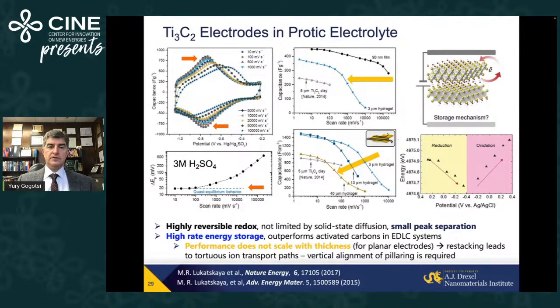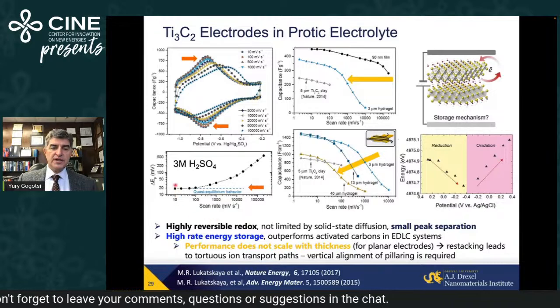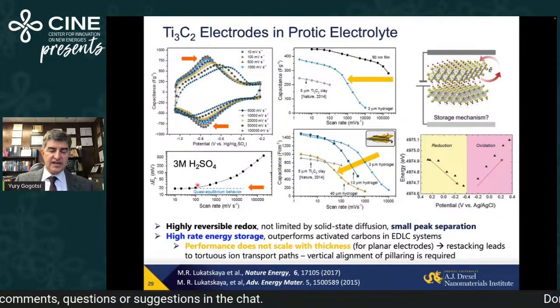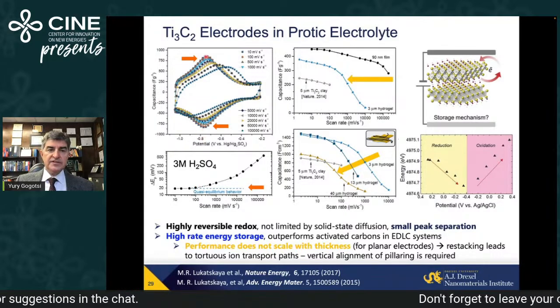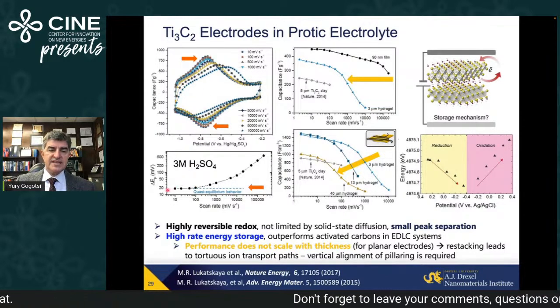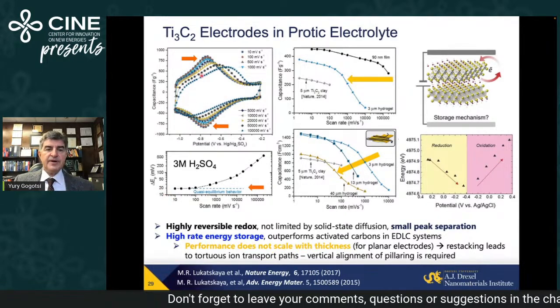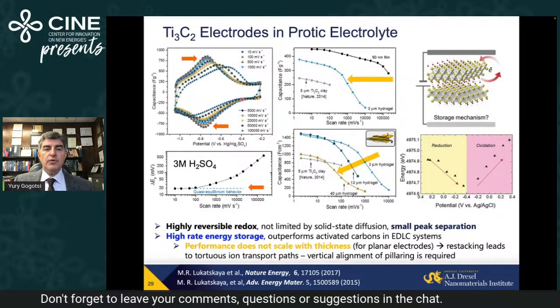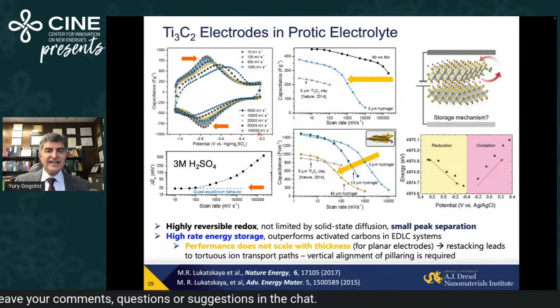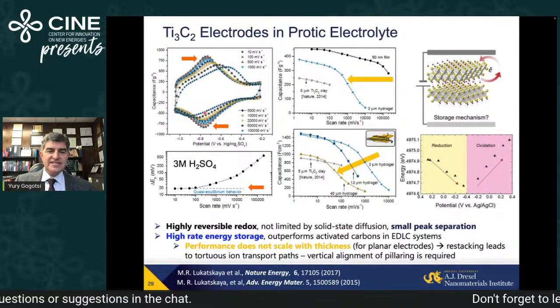What is also important, I try to convince you that these materials are good for high rate energy storage. And going back to Ti3C2 in protic electrolyte, sulfuric acid electrolyte, you will see this capacitive envelope, but then a broad but very symmetric redox, initially up to 100 millivolts per second. That's a typical supercapacitor rate. This redox is absolutely symmetric, less than 20 millivolt separation between the peaks. But even at 100 volts per second, 10 millisecond charge discharge, you can see it is still redox.